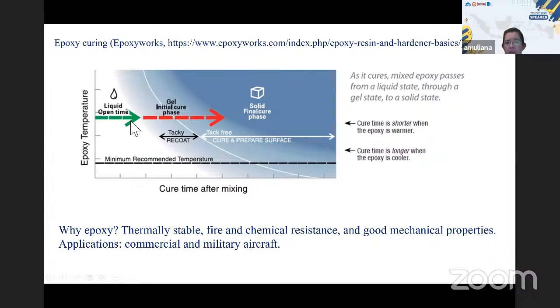So just to give a small background on the polymer or epoxy curing, right? It involves phase transformation from the liquid epoxy to the solid epoxy. It is often done at higher temperature to accelerate curing, although you can do it at lower temperature, but the curing process takes longer. During this curing, the curing reaction is exothermic, so it would generate a significant amount of heat. So it would increase the body temperature. And at the same time, during this solidification, there is a shrinkage. So we do have a competing effect between the expansion and the shrinkage.